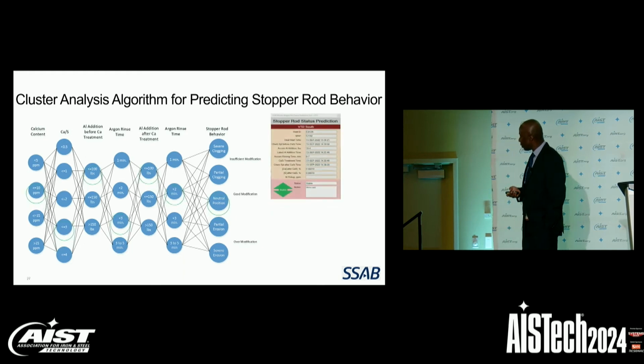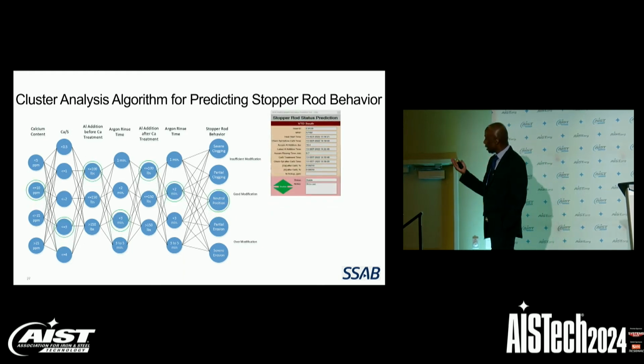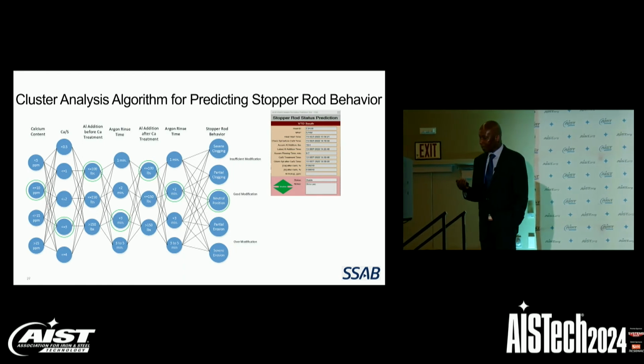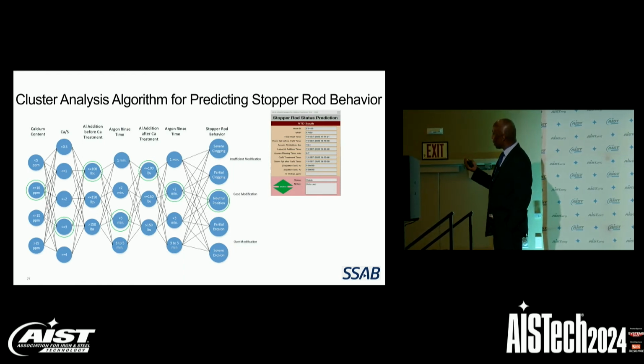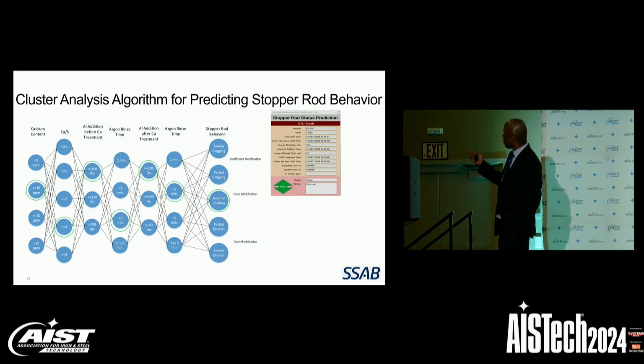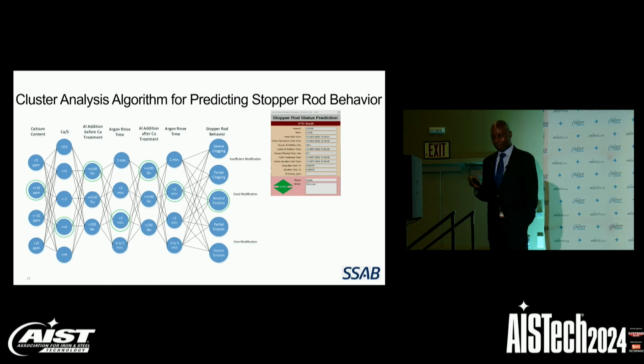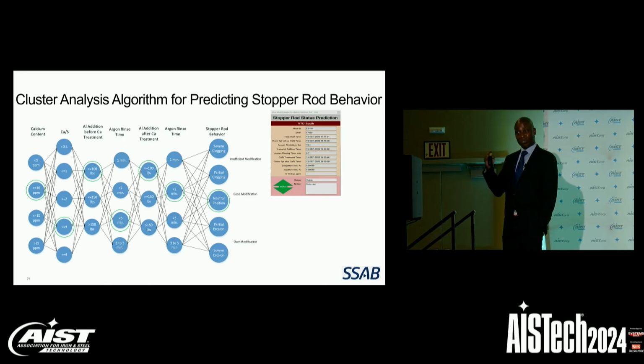For example, if you take a heat that ended up with 10 ppm calcium, calcium to sulfur ratio of about 3, an aluminum addition before calcium treatment of about 100 pounds, an aluminum addition after calcium treatment of about 100 pounds, and then with argon rinse time of about 2 minutes. This combination of process variables will lead to neutral position, i.e. no stopper rod erosion, no SEN clogging.